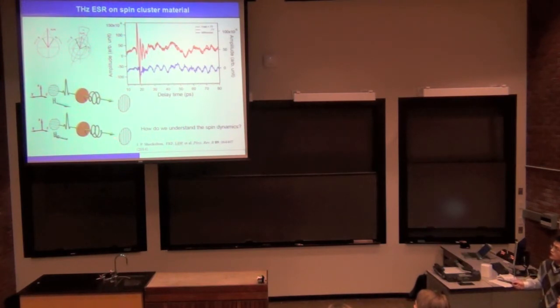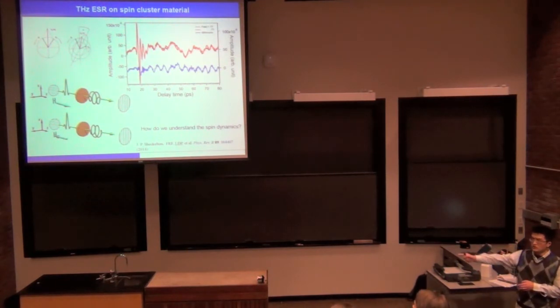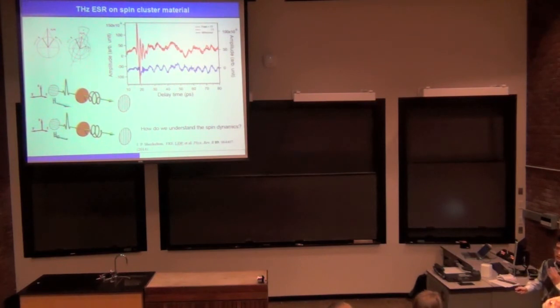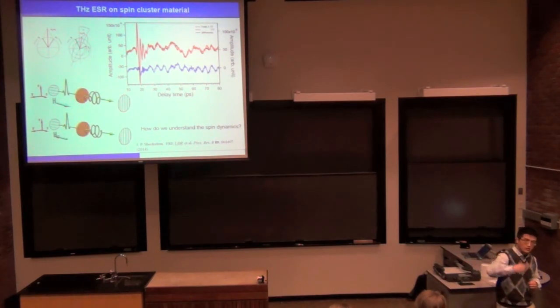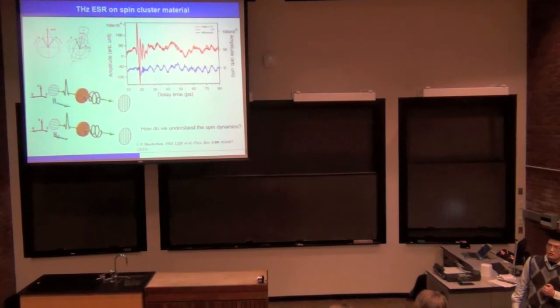In the Terahertz spectroscopy, we apply a magnetic field along the light propagation direction. And if you think about it, if you apply a magnetic field along this direction, then the spin would precess this way. So naturally, if the energy of the photon is right, the spins would absorb a circular polarized light. And then if you flip the direction of the magnetic field, then the spins precess in the other direction, so it would absorb a different handedness of the circular polarized light. So we measure the signal with the field at +7 Tesla and -7 Tesla. So we flip the field direction, and if we look at the difference, then you will see a nice ring of the signal that's due to the ESR of the spin system.